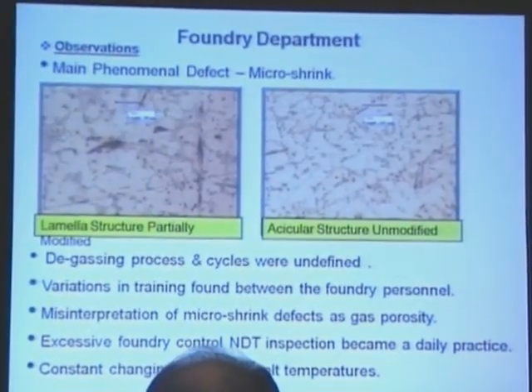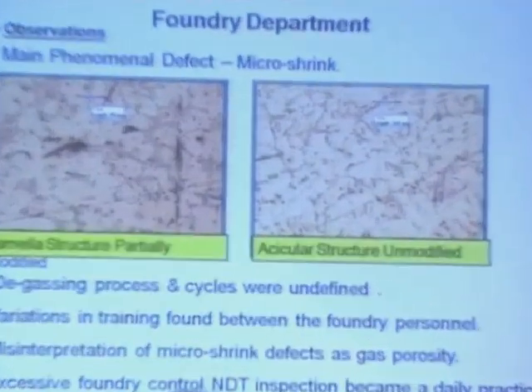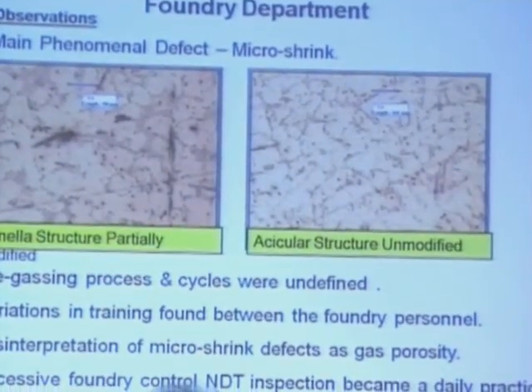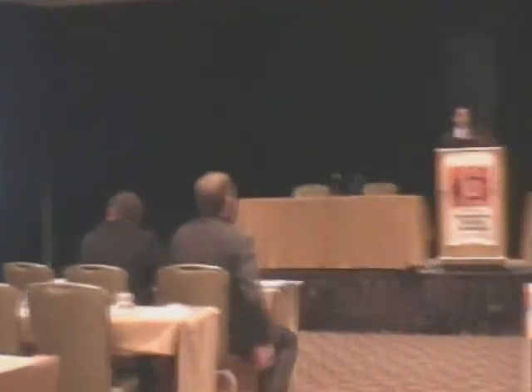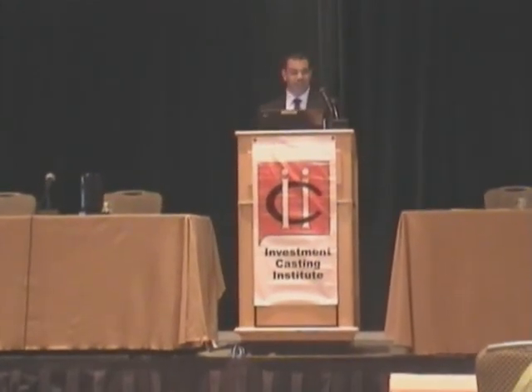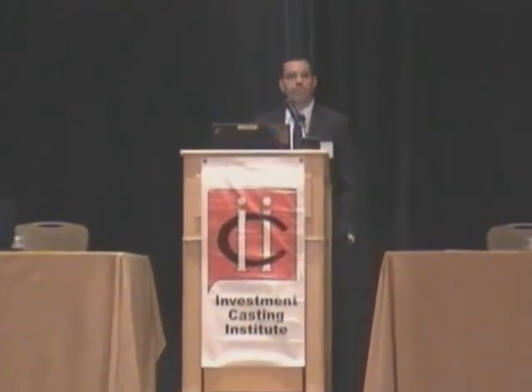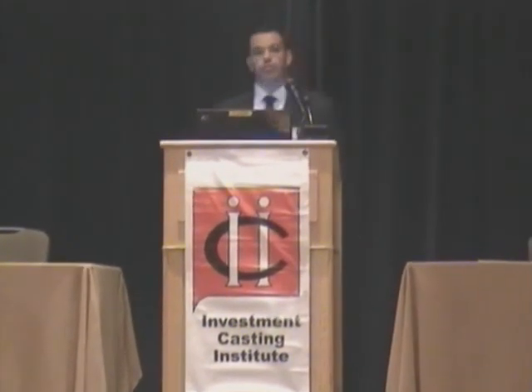So we went a little bit deeper into it, and we found out that our degassing process and the cycle were undefined. Practically the workers, the foreman and his guys were doing it on a daily basis, but they were the only ones that knew how to do it. And we spoke about it in the morning. If one of them should go, we don't know even how to operate that. Now we found out variation in training in the personnel itself. One of them was doing it for 20 minutes, while the other one was doing it for only 10. They were playing with flow ratios of volume. They were doing different stuff, nobody knows what.